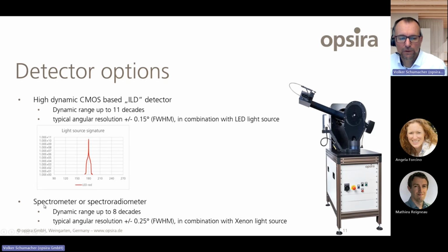Further, we can mount a spectrometer or spectroradiometer to the goniometer. Here, the dynamic range is a little bit limited in respect to that sensor. Compared to that sensor, it's still 8 decades, but then we have the result spectrally resolved. The typical angular resolution is a little bit higher, with 0.25 in combination with a broadband xenon light source, which we have to use for this.